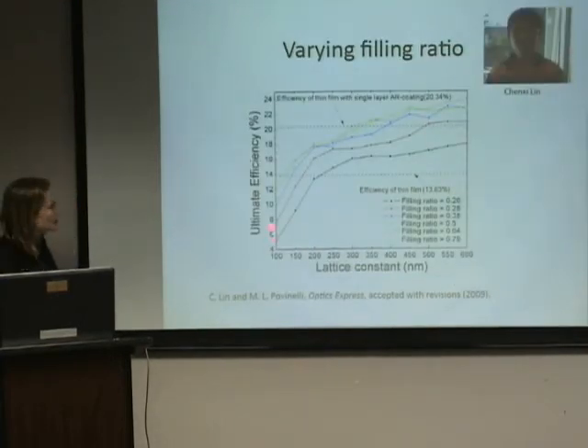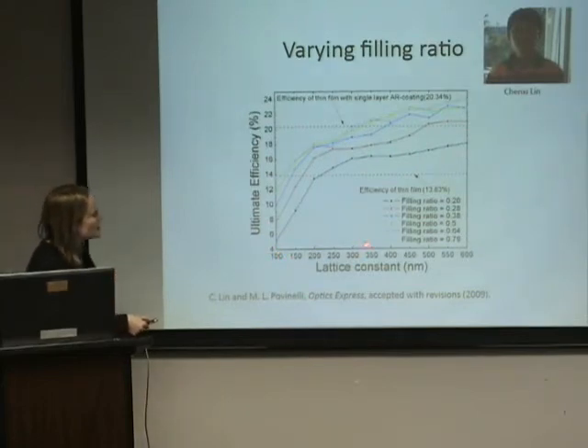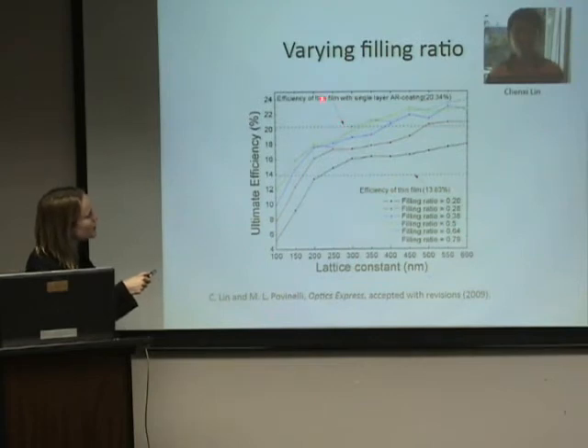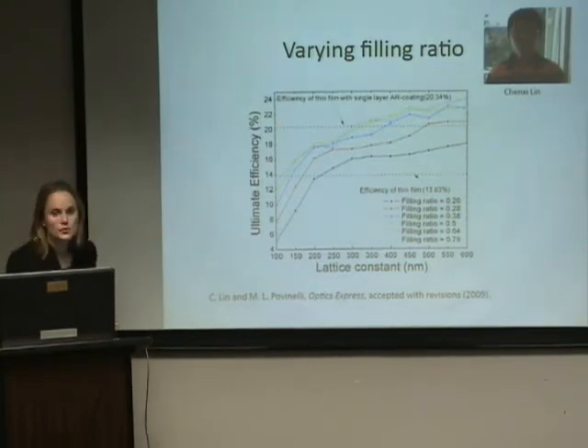And here's what happens when we calculate the ultimate efficiency as a function of lattice constant. Remember, all the previous studies were down here at 100. As we increase the lattice constant, then for a given filling ratio, so let's take the black line, that's 0.2, with an increase in lattice constant, you just do better and better. This is the thin film efficiency for comparison. So you can see already we have a whole number of structures that are better than a thin film. And if you increase the filling ratio and optimize that filling ratio, you can see that we actually do better, not just than a solid thin film, but you do better than a thin film with an anti-reflection coating, which is shown here. And so we can get considerable absorption increases.